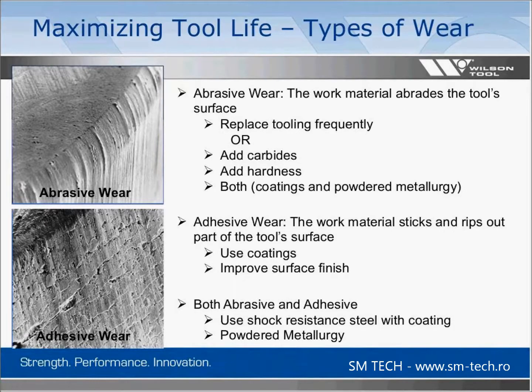Second, adhesive wear. Adhesive wear is where the work material actually sticks and rips out part of the tooling surface. To battle adhesive wear, you can look at surface enhancing coatings, or you can improve the surface finish of the tool. What I mean by improving the surface finish of the tool, you can actually polish the cutting surface of the tool, or in some instances, a bead blast even makes a difference.